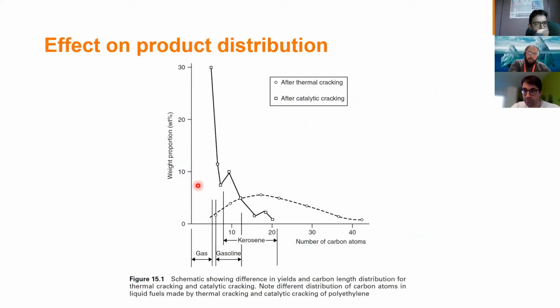This is exactly the same thing, but in a different manner. This picture shows you the cracking of polyethylene with a thermal cracking mode, and then a catalytic cracking mode. With the catalytic cracking mode, you see this sharp and narrow range spectrum of products: gas, gasoline, kerosene. That's it. But on the other hand, if you have a similar pyrolysis done thermally, the range of hydrocarbons is huge. You get lots of waxy and high-end molecules as well. This is why catalytic pyrolysis can be advantageous.